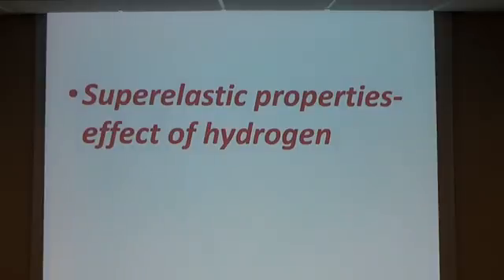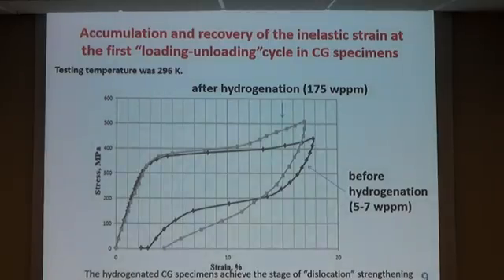Superelastic effect and hydrogen. This is accumulation and recovery of inelastic strain at the first loading-unloading cycle in coarse grain specimens. Testing temperature was room temperature. After hydrogenation, compared with before hydrogenation, the hydrogenated coarse grain specimens achieved the stage of dislocation strengthening earlier as compared to unhydrogenated specimens.